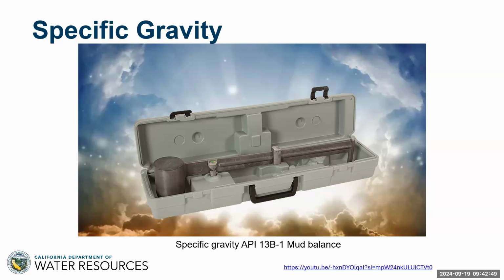However, if you suddenly measured this and you found that you had a specific gravity of 1.4, that would say that the fellow who was running the grout plant got the water content wrong. And it's crystal clear. You can get specific gravity to within 0.02. And that's a typical operational variation. And that is more than enough to confirm that your batching quantities have been accurately done. Next slide.